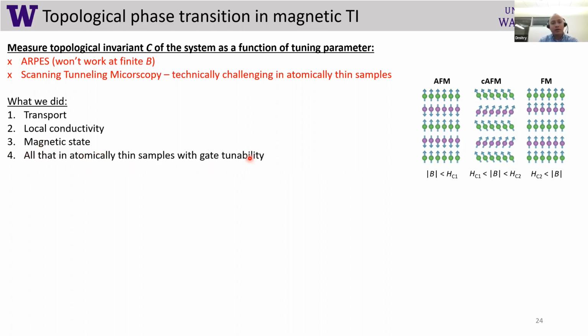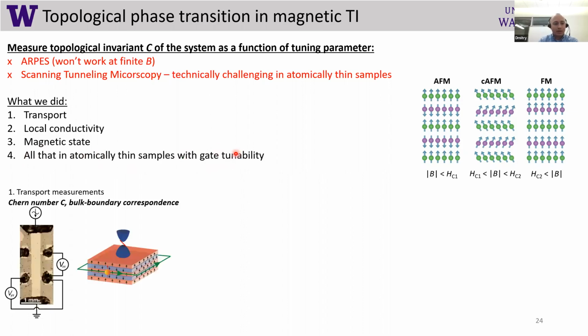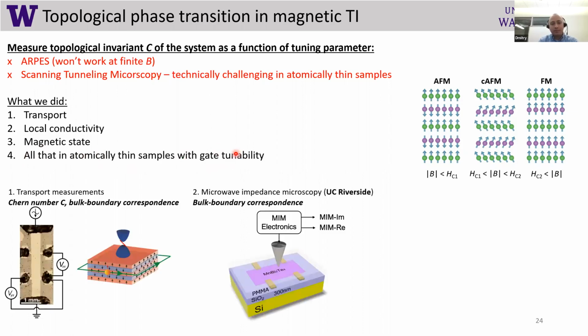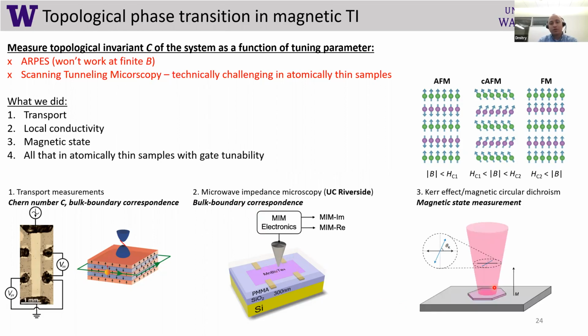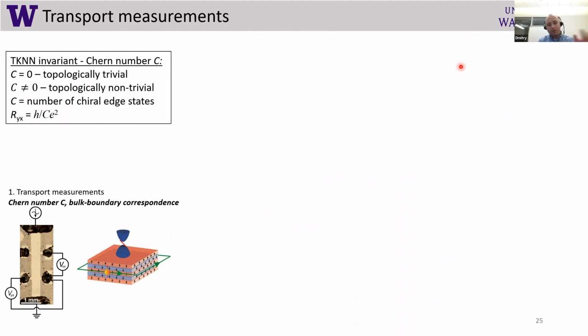And all this is done in atomically thin samples with gate tunability. So as I said, transport informs us on Chern number. We also collaborated with Professor Yong-Tao Cui from University of California, Riverside, who helped us to understand the bulk conductivity and also to map out the edge states. And finally, we used local mapping of magnetic state to understand magnetism in the system. And this allows us to understand bulk gap, edge states, and topological invariant. So now transport will be one of the key methods I'll be using, and it allows us to extract this TKNN invariant or Chern number.